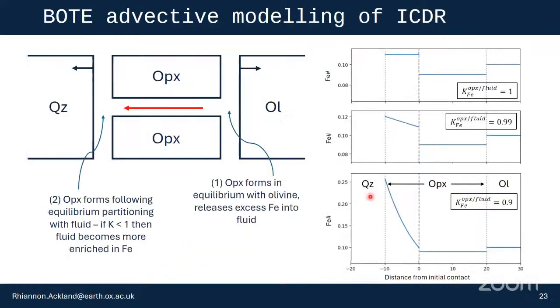And actually, I've done just a little bit of a back of the envelope model of this. If you suppose that the olivine and the orthopyroxene that forms at the olivine interface is in chemical equilibrium in terms of the iron number, as I mentioned, this means that the orthopyroxene has a lower iron number than the olivine. This then releases excess iron into the fluid, which due to the formation of void space gets sucked into the quartz interface.